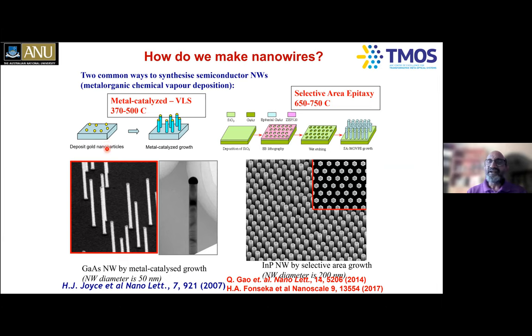And then it ends up creating this alloy liquid of gold-gallium, and then we introduce gases needed for the growth of gallium arsenide, trimethyl gallium and arsine. These gases really dissolve in this liquid, it gets supersaturated, and crystals start precipitating out, and gold is always sitting on the top here. And this is essentially like if you're dissolving sugar in water, and above a certain concentration, the solubility limit is exceeded, and sugar crystals start precipitating out, or salt crystals start precipitating out, if you're using salt. The same physics is happening here as well.